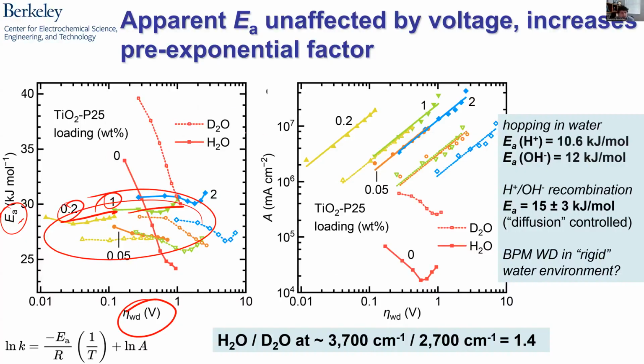There's also a kinetic isotope effect. So obviously protons are involved in this reaction. With deuterium, it's a slower reaction. You can compare these activation energies to those for just protons hopping in water. And in this case, they're significantly larger, though we have catalysts that make that better. And one of the hypotheses is you're moving protons in a very different local environment than bulk water.